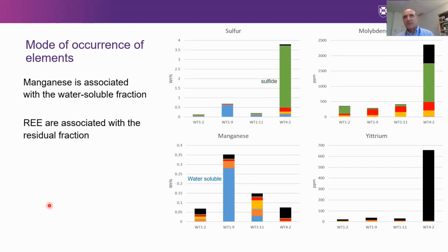Whereas manganese, for example, is associated with the water soluble fraction, so you can see that in the blue color. And rare earth elements were associated with the residual fraction in a silicate form. So this is important both from the perspective of toxicity and potential mobility, and also the perspective of potential extraction.